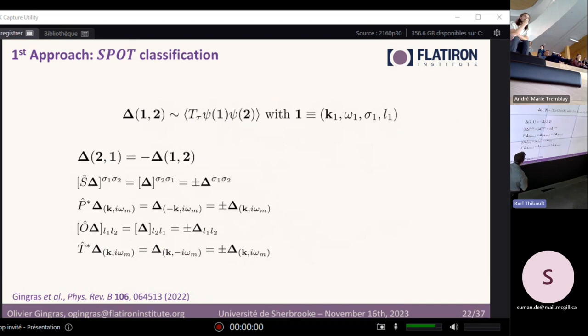Okay, so before showing some results, I need to discuss the symmetry classification here, because we have a few more quantum numbers, as Ian was foreshadowing. So now our electrons not only have momentum and spin, but they also live in a spin-orbital space here, the t2g orbitals. And because of the retardation of the pairing glue, they also depend on frequency. But again, if we exchange all of these quantum numbers, this gap function should be odd under such an operation. And if these quantum numbers are decoupled, then it will be odd or even under the exchange of each of these quantum numbers separately. So spin, momentum, orbitals, and time or frequency here.